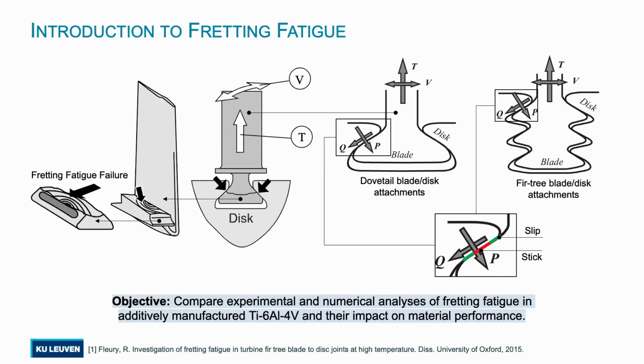This combination of contact load and shear load generates very complex loading conditions at the contact interface, in the way that the middle of the contact is sticking, and at the edge of the contact, we have partial slip at the micro level. So what happens there? The crack starts here because of the micro fretting, and then the crack propagates in mixed mode because of the contact situation and the shear stress distribution that we have here, and then propagates through the root of the blade. And then that causes the final fracture. So the main objective of this PhD work was to set up a testing and numerical framework so that we can test such a difficult condition in a controlled way.